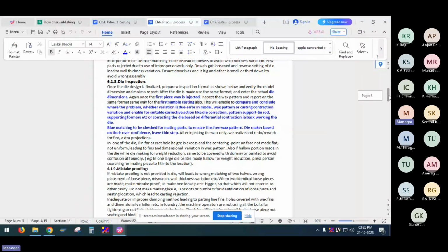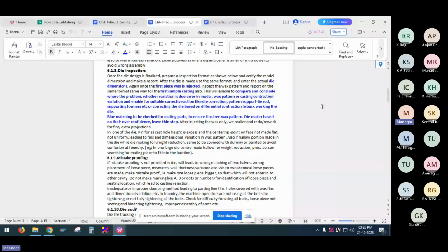And in some of the components, we assemble 2-3 wax patterns to form a single component. In that kind of situation, the die inspection should be such that the matching is perfect, without any gap or any fins, which will lead to additional fettling or cleaning operation during the assembly stage. So for that, we should insist the die maker do blue matching for the mating components and ensure that the wax pattern is very clean without any gap and any fissures in the parting lines.